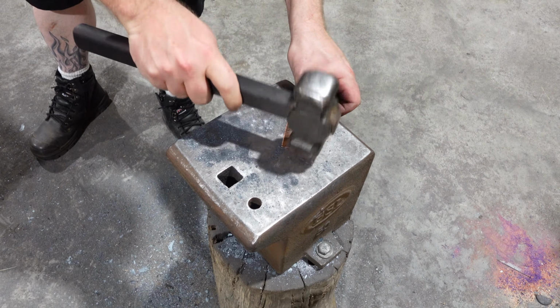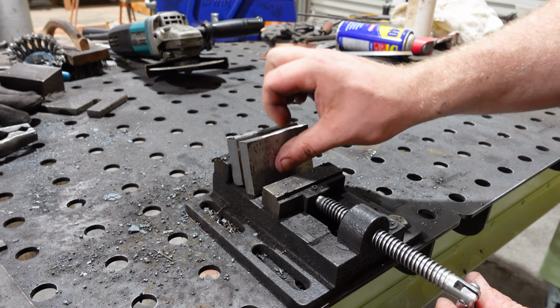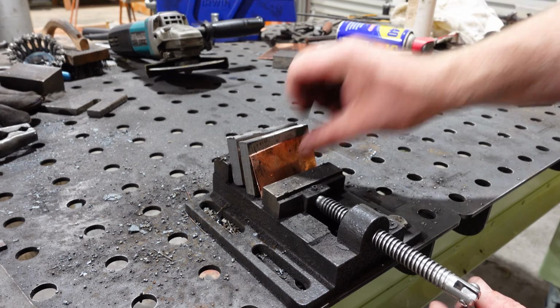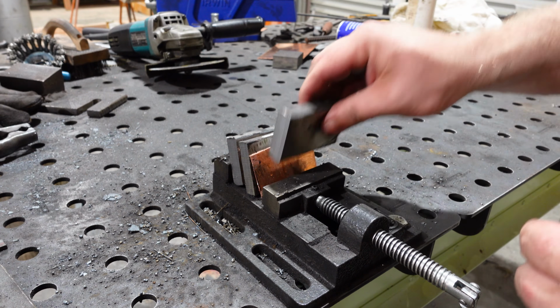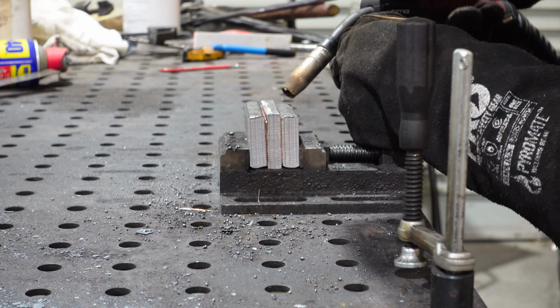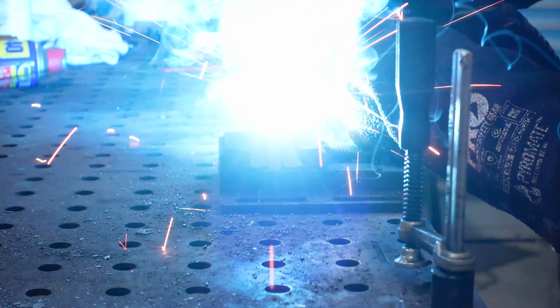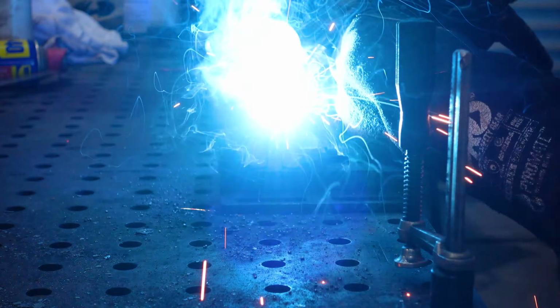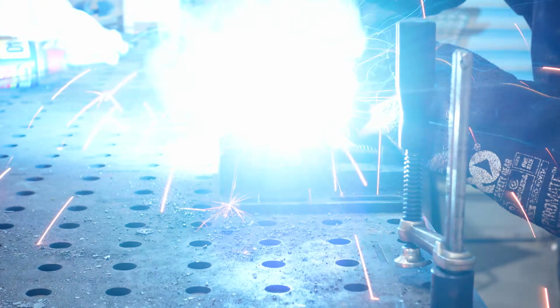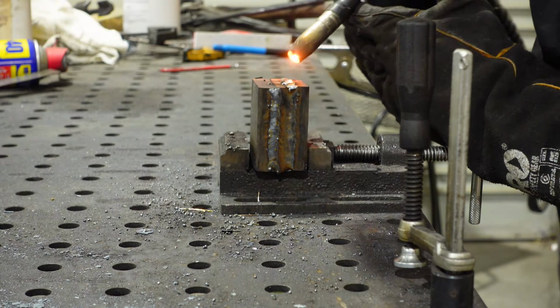Now I can get this one welded up tight, trying to leave no gaps. The reason this is making me uneasy is that the melting temperature of copper is so much lower than steel that if I happen to overheat the billet and squeeze too hard, there's a chance liquid copper could squirt out of the stack and burn anything it touches.